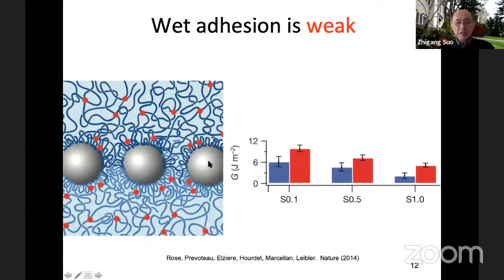So the specific thing is interesting. They use nanoparticles of silica, but silica doesn't form a covalent bond. It allows you some polymer adsorption. By this adsorption, they achieve adhesion energy. For people who know about this kind of number, energy per unit area—adhesion energy per unit area is about 10.